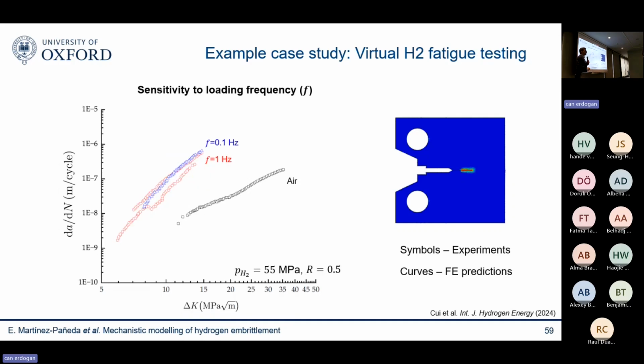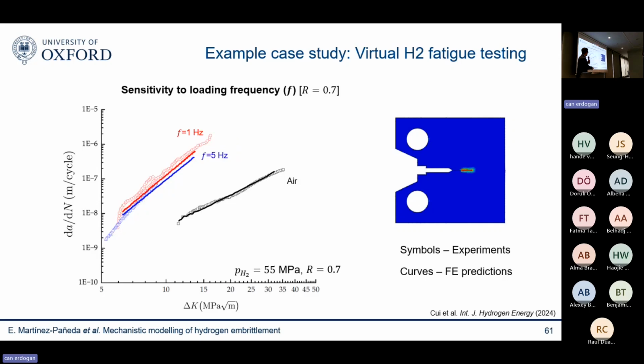And they also have data for different frequencies. Again, we just change the way we load our sample. We do not touch any of the parameters involved. This came out of the model. And this is for a given load ratio. They have data for a different load ratio. And again, a good agreement. All the data that we threw at the model was blindly predicted without any recalibration whatsoever. So we were quite happy about this. I must confess, I wasn't expecting such a good level of agreement.